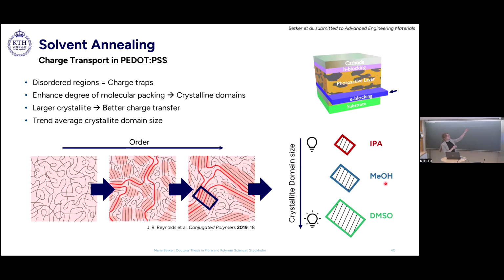And then, in red, these are conductive pathways here. And the more you do this, the more of these ordered regions, which we also call crystalline domains, will appear in your film, and they are highly conductive. So what we did here, we compared the average size of these crystalline domains in the polymer film. And again, the results very well correlate with our observations from the conductivity measurements. So for the isopropanol, we found the smallest crystalline domains, while for the DMSO, we found the largest ones.